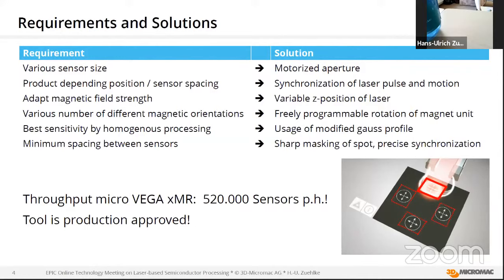Now we have different sensor sizes. We have different positions on the wafer, so we need a very nice synchronization of the laser and the motion system. We have to adapt the magnetic field strength for the different products and stack systems. We have different numbers of magnetic orientations. We need very homogeneous processing to get very sensitive magnet sensors. And at the end, if you like to do smaller devices, you have minimum spacing, and we need very precise positioning. To give you an example, we can do more than 500,000 sensors per hour. That could mean for a typical device, what we are just doing, 2 wafers per hour. The tool is already approved for production, and we are doing many more evaluations at the moment.